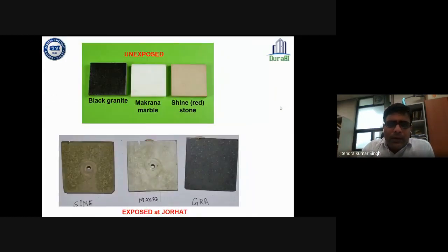These are the marble, Makrana marble, black granite, and red stone. This is unexposed. But if you see here, after 1 year of exposure in the Jorhat condition, the sandstone has some microbes, the color of the Makrana marble has changed, and the black granite has changed its color. It's very black, but here you can see the blackness has decreased due to the effect of the humidity. Jorhat is also very humid, and there are microbes in the atmosphere, because Jorhat contains coal. Coal contains some sulfur, and in the presence of sulfur, sulfur reducing bacteria grow. We observed here a sulfur reducing bacteria, which is decreasing the property of the marble.